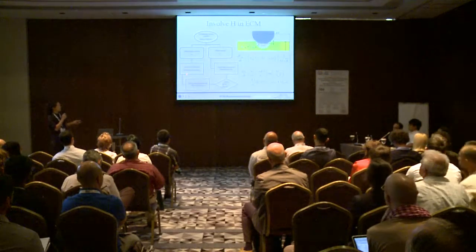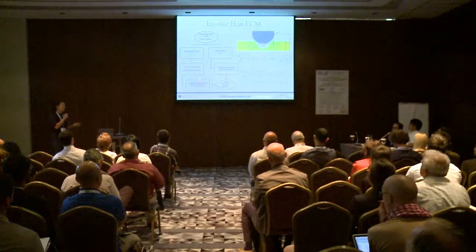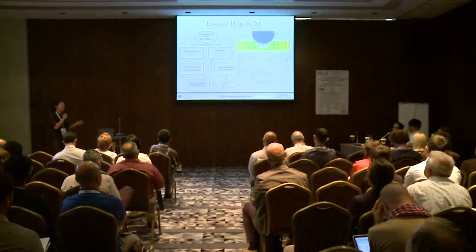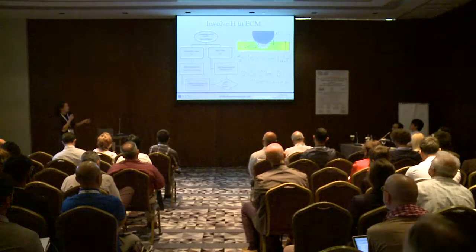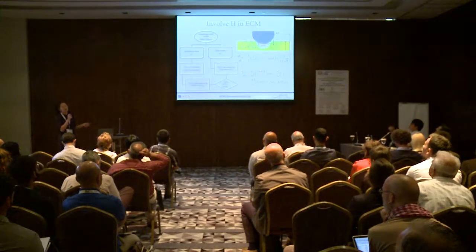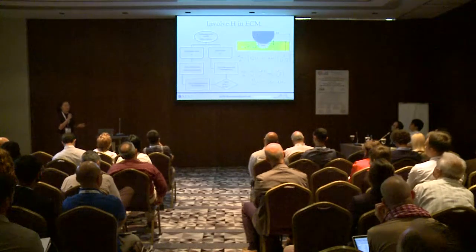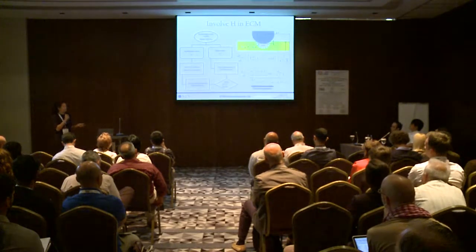This enables us to calibrate the hydrogen-induced solute drag applied to a dislocation. Combining the resultants of the two stress components, we obtain the ordinary differential equations during nanoindentation: the force evolution with time and the dislocation density evolution with time. By numerically solving the two equations, we obtain the force-displacement curve of the indentation in the hydrogen environment.